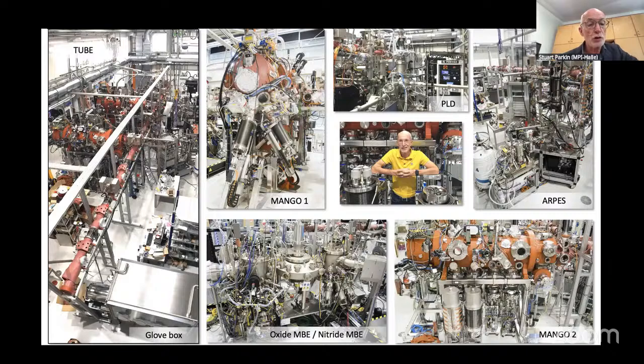This orange tube is 15 meters long. It's an ultra high vacuum tube. And we have built little robots that will pick up a substrate on which we deposit these ultra thin heterostructures and insert the substrate into one of these deposition systems. Let's say this is Mango. Mango is a homemade system which we designed to have up to 44 different sources of materials, either a magnetron sputtering source, an ion beam sputtering source, or an effusion cell, like as in a molecular beam epitaxy.